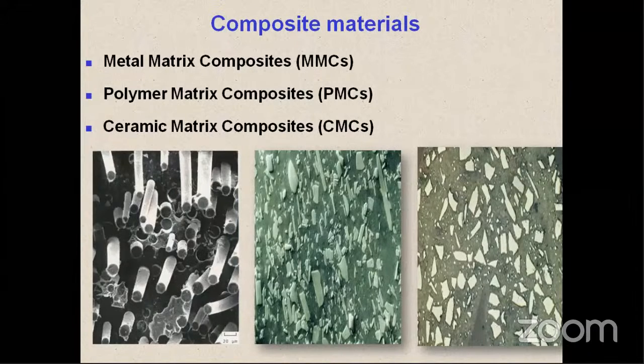And as I said, an alloy is different from a composite. When a composite material is fully cured, with high-end microscopy like scanning electron microscope or transmission electron microscope, you want to visualize how the nanoparticles are dispersed within the continuous phase, that is the matrix material, or how fibrous materials like glass and carbon are oriented, and how the bond between matrix and fibers is in the integral part of the component you made, even if it's a platelet structure like graphite or other particles at micron size or nano size, or whiskers which are dispersed and bonded well with the polymers or other metallic materials. Those interfacial aspects and dispersion aspects of the composites can be studied using a transmission electron microscope or scanning electron microscope.